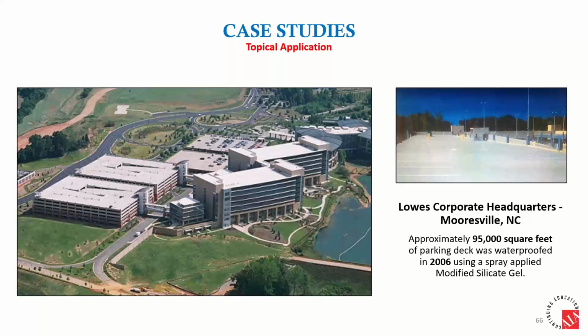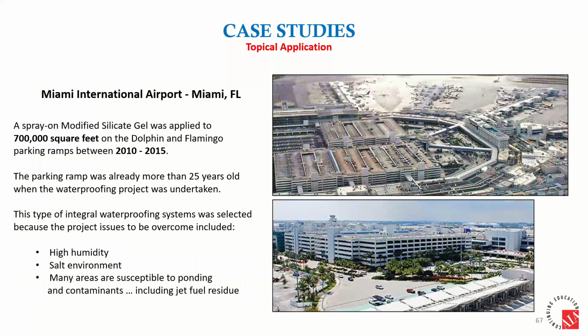And now we're talking about the silicate gel. This is the Lowe's headquarters in North Carolina. A number of parking structures there have been treated. Miami International Airport, over 700,000 square feet of parking structures there treated. Very difficult environment. The planes actually take off over these parking structures, spitting burnt jet fuel on them. And with the silicate gel being in place, the fuel can't penetrate.